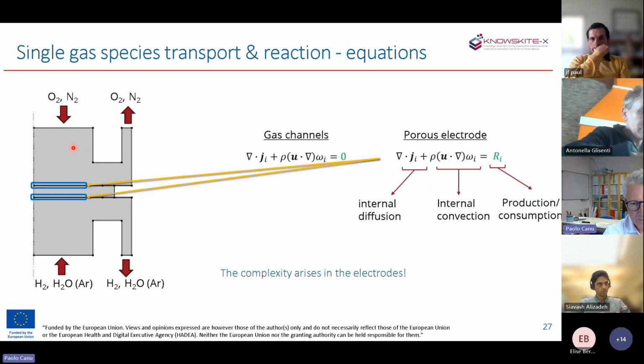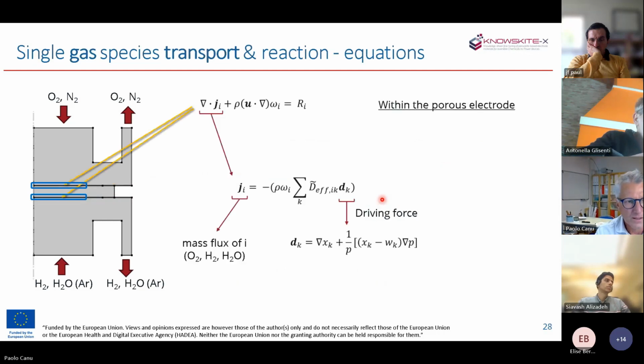And indeed, inside the porous electrodes, we have an additional term in the equation that describes the rate of production or consumption of gas species. Now we are talking about the species appearing on the sketch: oxygen, hydrogen, steam. Not intermediates on the surface. These are single gas species. So focusing on the electrode, the equation says that the species might travel, that's the transport of species, and the displacement is based on diffusion. The driving force for diffusion could be a gradient of pressure or a gradient in composition.